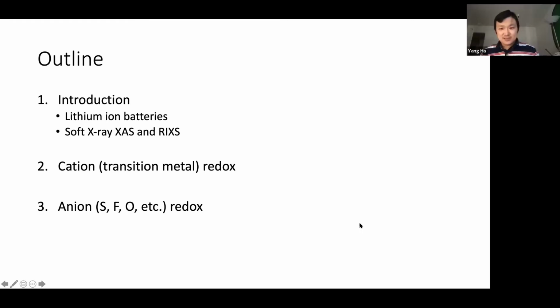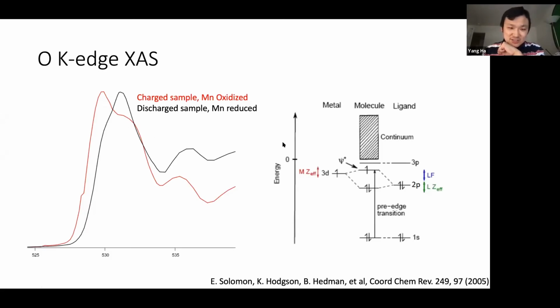Thanks. Okay. So we now switch gears from cation redox to anion redox. As I mentioned, the oxygen redox is now a very hot topic in the field. But unfortunately, in the field of batteries, when people are talking about monitoring oxygen redox, they always think of the oxygen K-edge X-ray absorption. So I think this is the right group of people to complain, because we all know the oxygen K-edge is really a transition from the oxygen 1s to the transition metal 3d that mix with the oxygen 2p. So the pre-edge here really reflects the property of the transition metal instead of the oxygen redox itself.